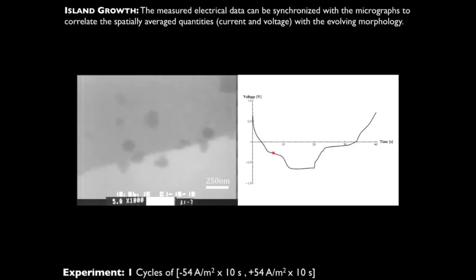We're using galvanostatic deposition and can also measure the potential. When doing electrochemistry you can measure two things — current and voltage. We're controlling the current, so the voltage is an output. What we see on the left is island growth: we apply a relatively low current density, and we see islands forming of copper, consistent with what is known in the literature. Here we're cycling — depositing for some time and then etching — and we get very nice cycling of these structures where we can deposit them and then strip them pretty efficiently. This shows our device and platinum electrodes are working well.